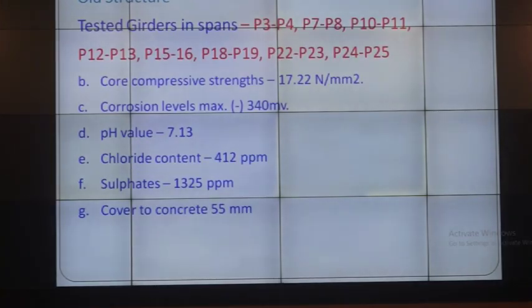Again, the tested girders, these are superstructure. I think earlier I showed you the substructure there. Here, superstructure, again, the core compressive strengths are on the lower side, it is less than 18. Corrosion levels 340, slightly higher, not acceptable. pH value gone case, it is absolutely miserable, it is 7.13.